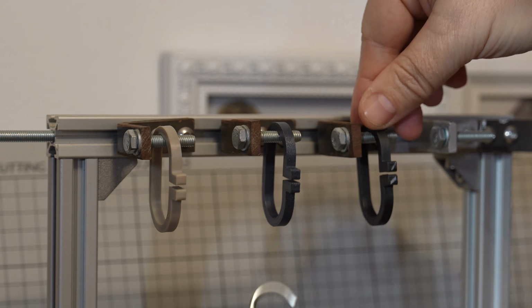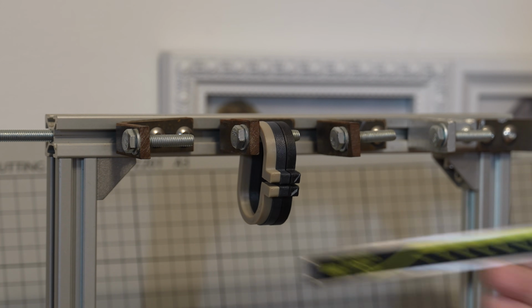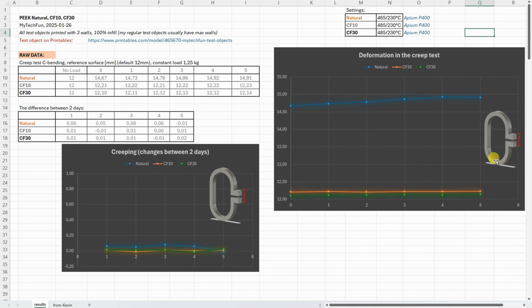And now let's analyze the numbers. On this graph we can see the distance between two reference surfaces, and yes, with the natural we can see some bigger initial deformation, and the two carbon fiber versions are very stiff materials. But with the creeping, what is important is the difference between days, and that's what can be seen on this graph. Here, yes, with the natural I could record some minimal creeping in the first 4 days, but these are extremely small values. With the carbon fiber versions I couldn't record any changes. This is some inaccuracy in the measuring. So in all 3 cases there is good resistance to creeping.